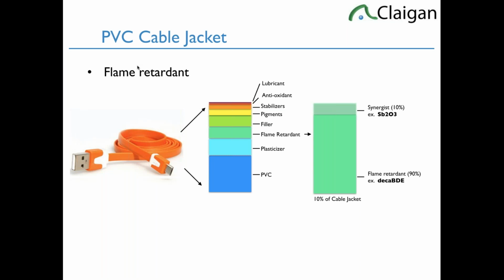And so basically it damps down the exothermic or energetic effect. So if you have antimony with the brominated or chlorinated flame retardant, you need a lot less of it, because in combination, they do a much better job of damping down the hydrogen radicals, the overexcited hydrogen particles, and stop the runaway fire we can have with PVC. So most flame retardants, especially the halogenated ones, it could be Dechlorane Plus, it could be decaBDE, normally end up with the antimony trioxide synergist. They enable less flame retardant to be used to create the same flame retardancy. So when you look at a flame retardant, you almost always have a flame retardant and a synergist, especially in the halogenated ones.